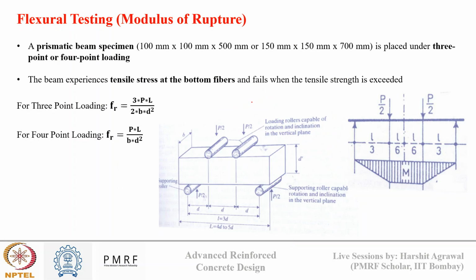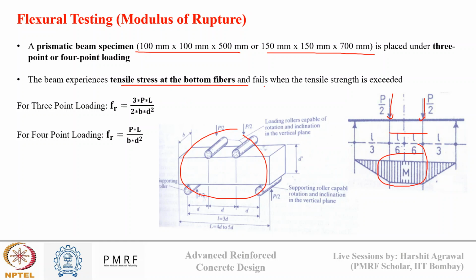and then we have flexure testing, in which we have a prismatic beam of 100 cross 100 cross 500 or 150 cross 150 cross 700, and it is placed in 3 point loading or 4 point loading. So if you draw a bending moment diagram of this 4 point loading setup, what you will observe, there will be a part in between which will be subjected to constant bending moment, due to constant loading that is acting from the top. And this part which is under pure tension is then used to estimate the tensile stress of the bottom fiber and the failure when the tensile strength is exceeded.